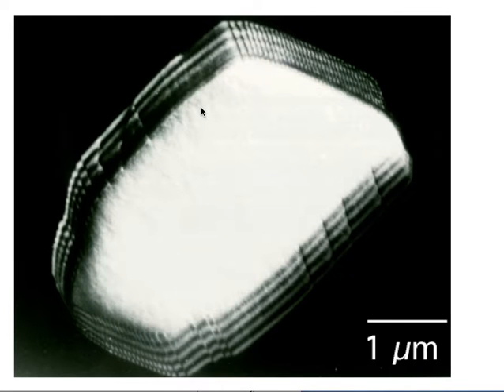Okay, so you really can observe these dislocations in the transmission electron micrograph. You can even determine the Burgers vectors because you do a certain experiment in which the contrast from the dislocation completely disappears, and from that information you can determine the Burgers vector.